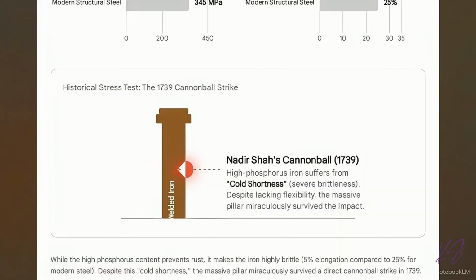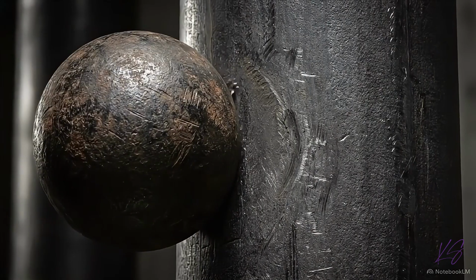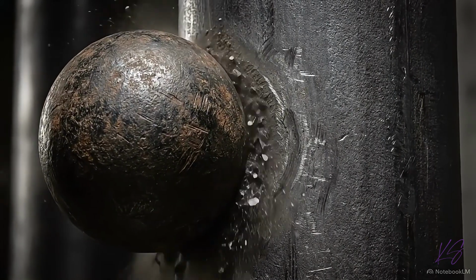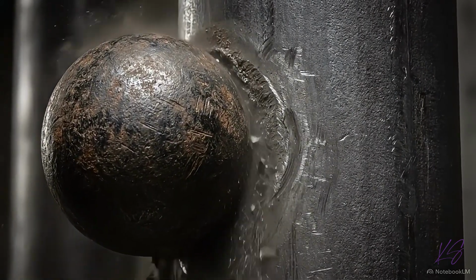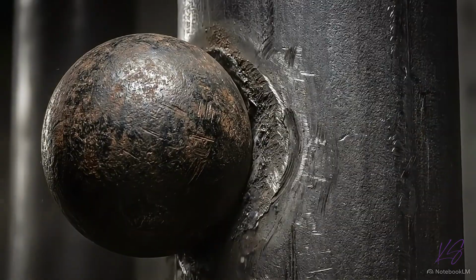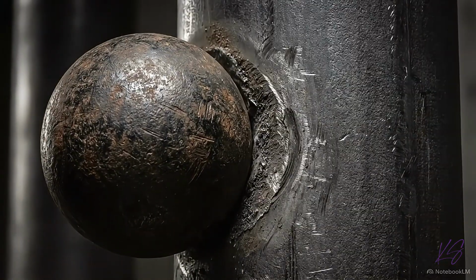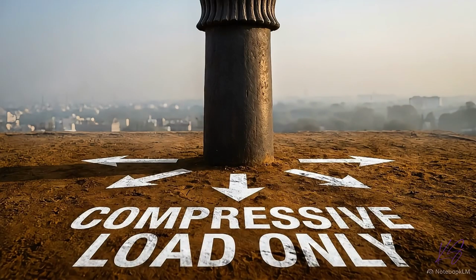The lower diagram illustrates a historical stress test. In 1739, an invading army fired a heavy artillery cannonball at the shaft at point-blank range. Despite the metal's brittleness, the massive, uneven, slag-filled microstructure absorbed the kinetic shock. The cylinder dented, but it did not shatter. Ancient smiths used this durable, brittle alloy for a specific architectural role, a vertical monument designed to support nothing but its own weight.